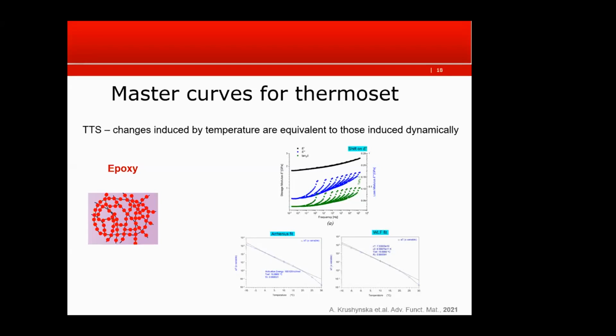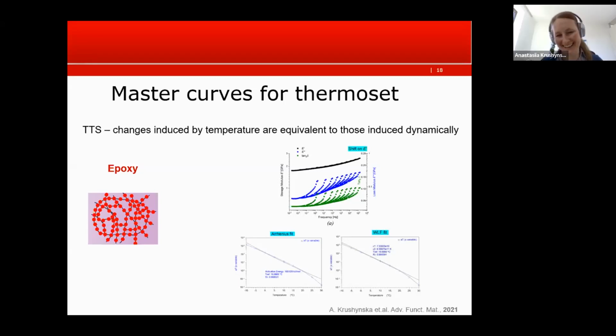And the other thing that occurred to me right now is all your shifts are based on the storage modulus. So you haven't shifted based on the loss modulus or the tan delta or the average value. Yes, this is an example. We did all kinds of shifts, and other shifts can be found in the supplementary material of that paper. So we did the shifts on the storage modulus, also on averaged values. It just does not work.